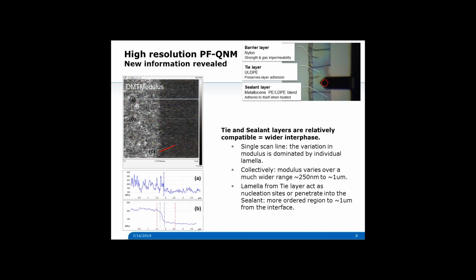But if we look at the modulus map, then it clearly shows up in the average. We see that essentially the individual lamella are still very sharp and they're narrow. But if you look at the average here over the image, again you see a drop, and this drop is happening on a range of a couple hundred nanometers to around a micron.